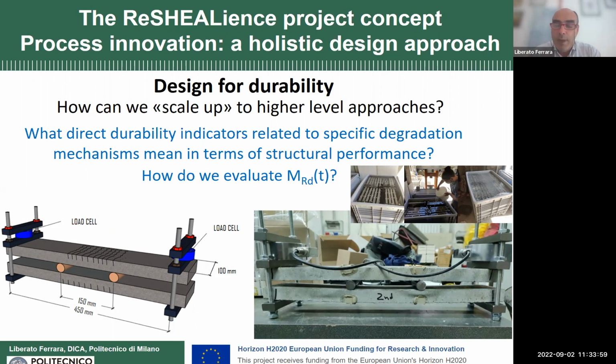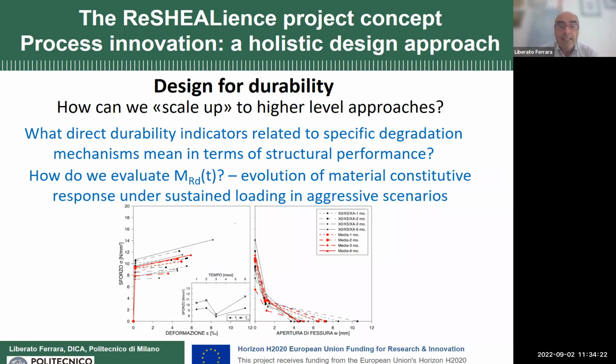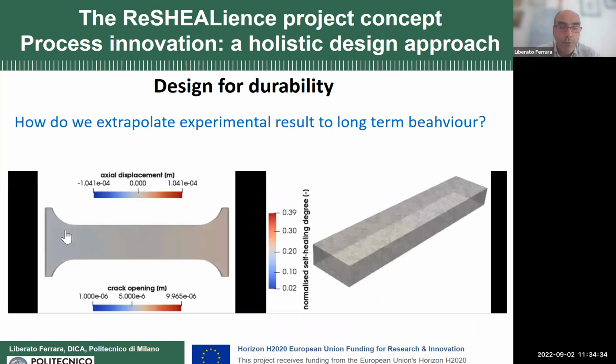It's not exactly that we are losing completely the layer which is attacked. We wanted to see how the combined mechanical and environmental action affected the constitutive law of the material. So we developed a setup to keep our beam specimens under sustained stress while they were being exposed to chloride solution, to sulfate water. And so we identified how the constitutive laws change over time, and we performed experimental identification up to 1 year. And then we went with some kind of numerical modeling.